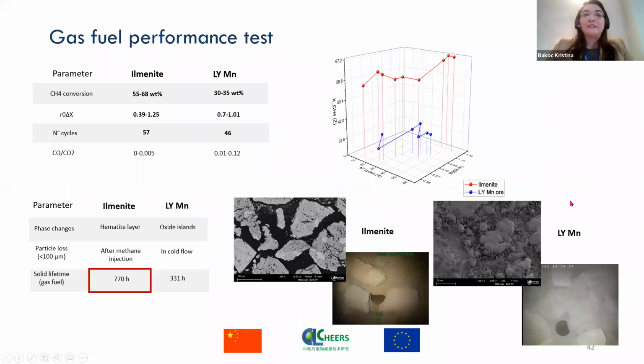What we have found following the gas fuel performance tests in the reduction atmosphere of methane is that ilmenite ores achieve high conversions of methane, as you can see in the red points here on the right, while the conversion with LYMN is lower in the case of methane or gas fuel conversion. And this would indicate that LYMN is more sensitive to high reduction atmosphere than is ilmenite. However, in the performance with solid fuel, LYMN would achieve significantly higher conversions. So this is the performance in the highest possible reduction atmosphere that we see here.